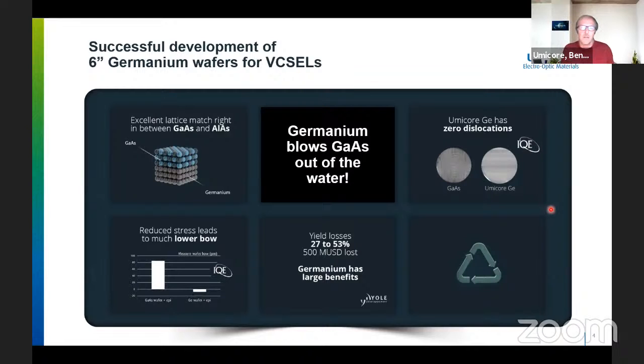As you know, a VCSEL is made out of two Bragg reflectors with active layers in between. Now, the Bragg reflectors are typically made out of a combination of aluminium arsenide and gallium arsenide, so aluminium-gallium arsenide. If you look at the lattice constant, the lattice constant of the combination of those two materials is actually spot on germanium, but it's not perfectly matched to gallium arsenide itself. Which means if you grow thick DBR layers, you see in the graph at the bottom here that you have quite significant bow in your wafer during growth, which means that you have issues with the uniformity of your growth on gallium arsenide, which on germanium you don't have, no bow at all.